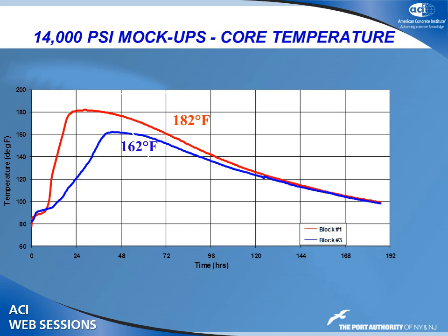Now, again, there's a lot of concrete out there that perhaps does that. This one here with 300 pounds of cement peaked at 162 degrees, but it took almost 2 days to get there. So we said, we'll take that one. We'll take the 162. Now, let me show you some core data from these two.